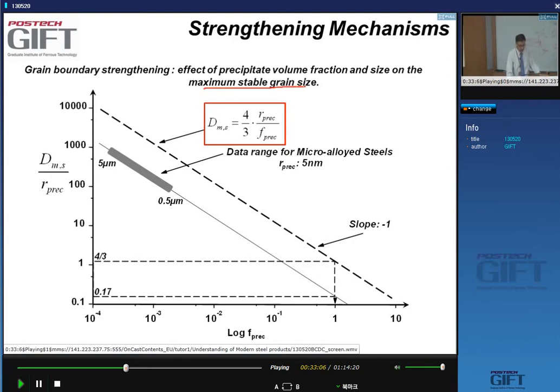The maximum stable grain size that you can have in a material in the presence of precipitates with a radius r and a volume fraction f. So if I rewrite this Zener equation, it tells me that this maximum grain size divided by the radius of the precipitate is proportional to 4/3 times 1 over the volume fraction of the precipitates. So it's a very simple law.